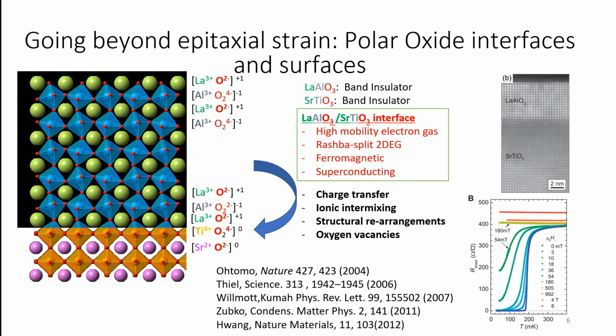People have studied why this emerges, and there are many different reasons. But the main understanding is that lanthanum aluminate you can think of as a polar material, because if you look at the charges of each of the constituent elements in each layer, in this layer here you have lanthanum and oxygen, and if you sum up the oxidation states, it has a net positive 1 charge. And so there's this alternating plus minus charge as you increase the film, as you go from the interface with STO, which is neutral, up to the surface.